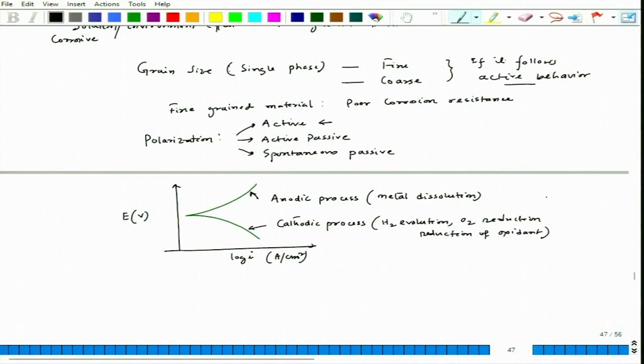Now both these polarizations are basically activation controlled, and there is no signature of attaining passivity. So that time the fine grained one would have a higher corrosion rate. If we try to see it in this same diagram, let us draw for the fine grained one. The fine grained one will show a plot like this. So this is for fine grain, and this is for coarse grain. This is a general trend for a material when it shows active behavior.